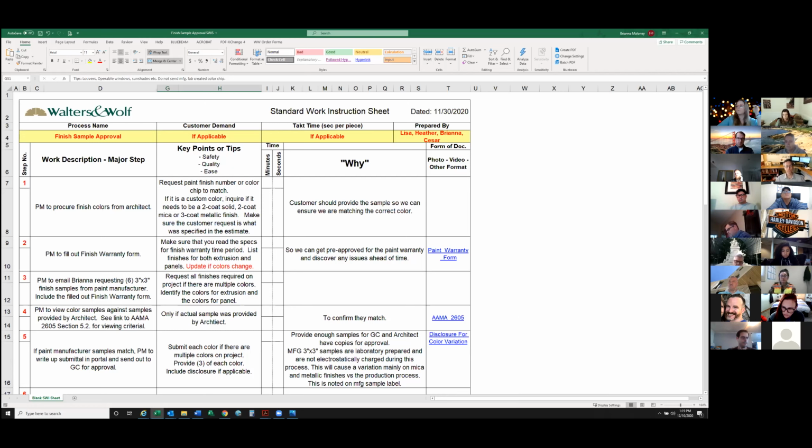And then Walters & Wolf is good at doing a production line match, establishing whatever early, and then they're confident that they can reproduce the same thing with a different batch of paint at a later date when they actually extrude. When they provide us those production quality samples, if that's what we're going to call it, they're actually retaining a piece of that for the project. And then when they go to paint the project, they're making sure that they stay within the 2 deltas of what they provided us.